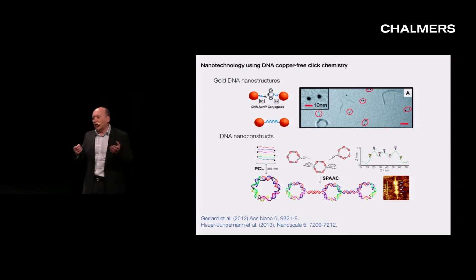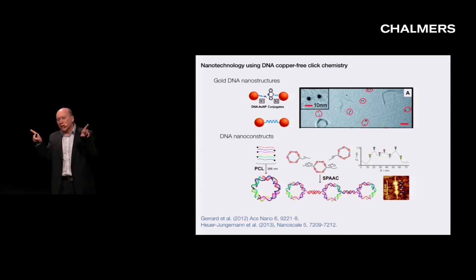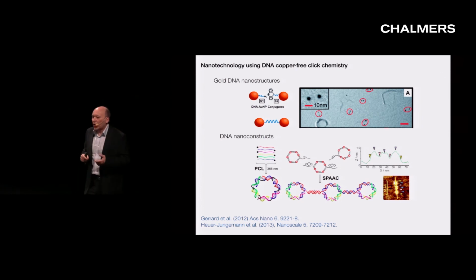And we've done the same thing using a gold nanoparticle with two DNA strands, which is divalent. And we can create two single bonds, one gold nanoparticle with two bonds to join three gold nanoparticles together. I just didn't put the images on this overhead. So we can control this stoichiometry of linkage.